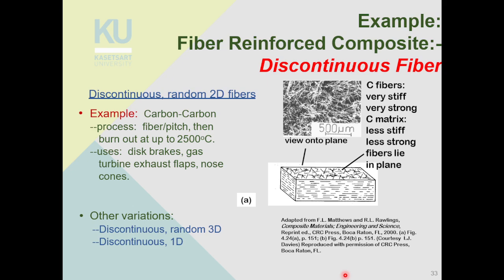So to make this, you dip the carbon fiber inside a pitch, which is some sort of tar, a really thick hydrocarbon type thing. Right? You dip it in there, compact it into the shape you want, and then you burn off the hydrocarbon. Right? So you are left with the carbon matrix that is bonding to the carbon fiber, right, at 2,500 degrees Celsius. We use this in disc brakes, gas turbine exhaust flaps and nose cones. Right, nose cones in rockets, gas turbine exhaust flaps in jet engines, disc brakes in a brake pad, right?